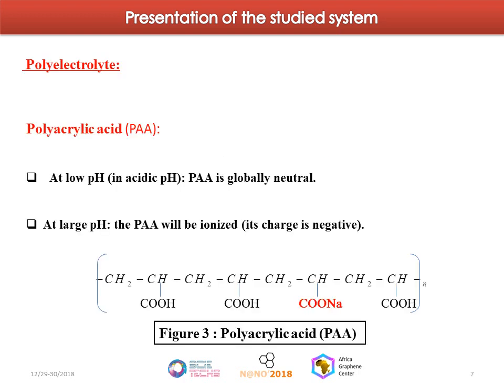And after the preparation of the microemulsion, we added the polyacrylic acid PAA to the microemulsion, and this polyacrylic acid is a weak acid with a molecular weight equal to 250,000, and its monomer mass equal to 72, corresponding to 3,478 weak acid groups per microemulsion droplet.